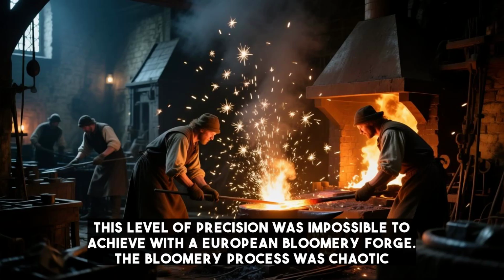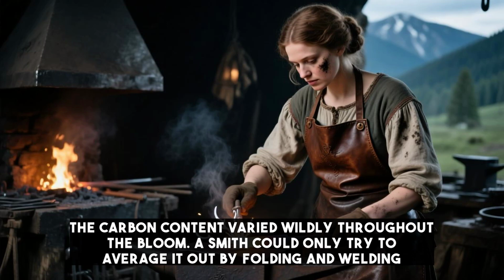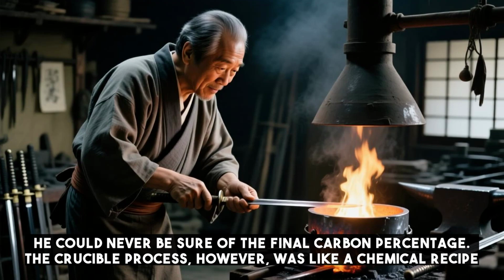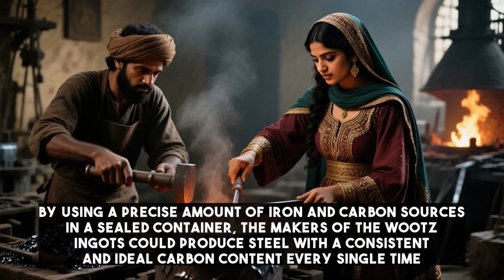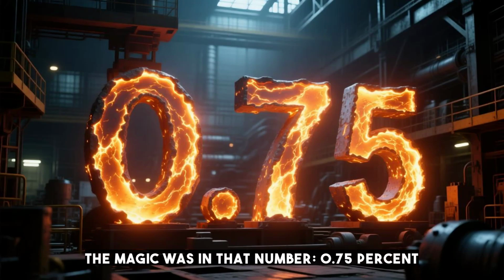This level of precision was impossible to achieve with a European bloomery forge. The bloomery process was chaotic. The carbon content varied wildly throughout the bloom. A smith could only try to average it out by folding and welding. He could never be sure of the final carbon percentage. The crucible process, however, was like a chemical recipe. By using a precise amount of iron and carbon sources in a sealed container, the makers of the Wootz ingots could produce steel with a consistent and ideal carbon content every single time. The magic was in that number, 0.75%.